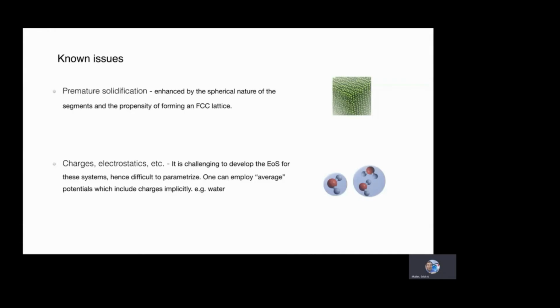The other thing that is missing is the explicit introduction of charges or electrostatics. In principle, there's nothing impossible about this. The issue is that it's very challenging to develop equations of state for these systems. Hence, it's very difficult to have the equation to be able to use it in the simulations. We have stepped around this in the model, for example, by looking at water. In this case, we employ average potentials, which implicitly include the charges. But we definitely recognize that this is an area which probably requires some sort of improvement.